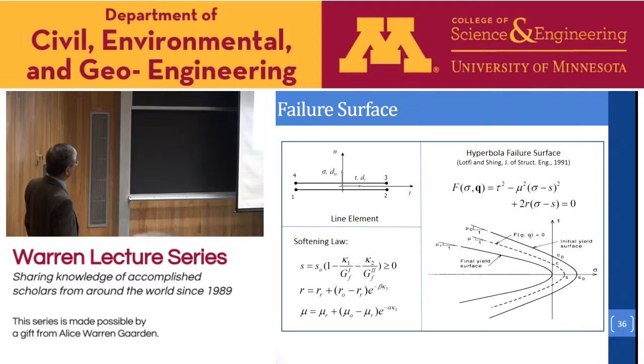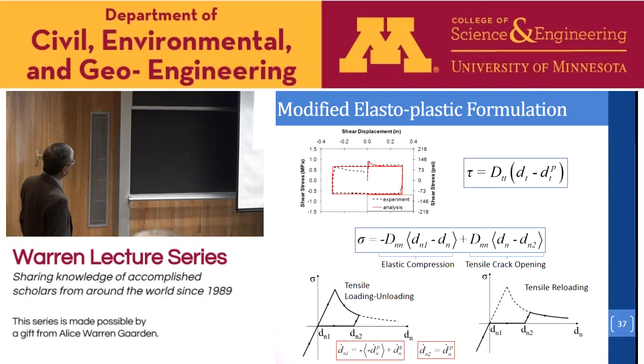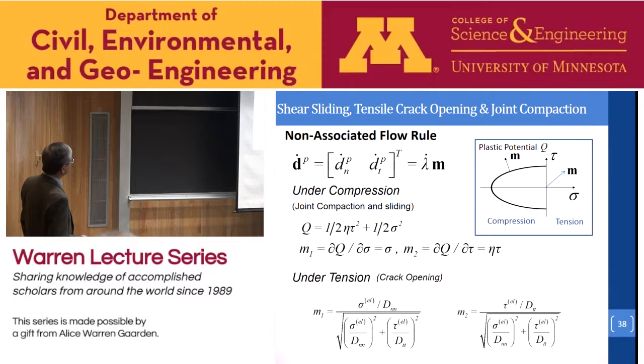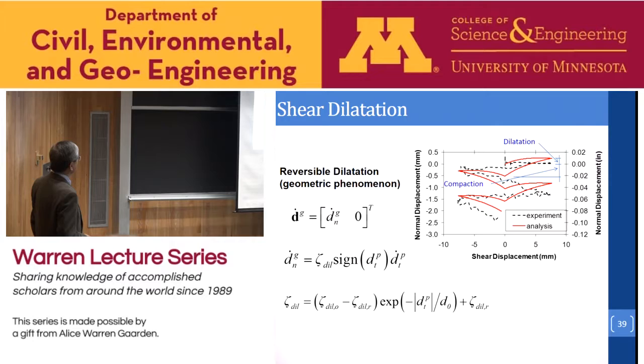This is the failure surface we used to control the mixed mode failure, the tensile and the shear failure of the joint. And this is a softening law which governs the shape of this surface. And we use a very simple modified elastic plastic formulation to model the shear sliding and also crack opening and closing. And this is the plastic flow rule used to model the joint compaction behavior when the joint is subject to a compressive stress. And under tension, crack opening, we use a modified flow rule. It's very similar to a stress return law. Now, shear dilatation is a geometric phenomenon, so we account for this using this simple geometric expression. So the dilatation is related to the sliding along the joint, okay?